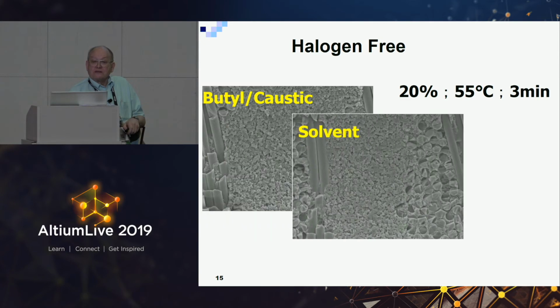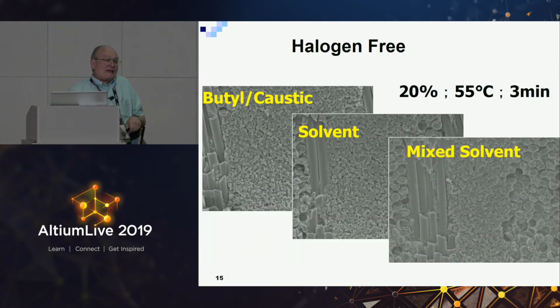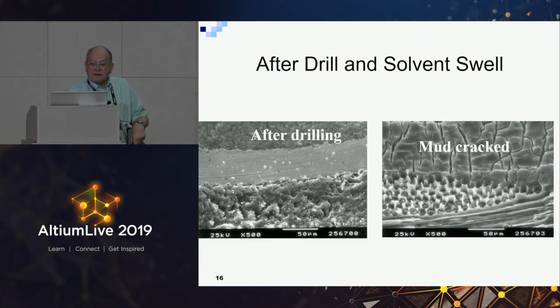The problem is that the halogen-free has a different smear because they've changed the resin content. So depending on the materials you pick, have the fabricators done their homework in terms of adjusting the smear removal process to match this particular kind of halogen-free? The materials are not all the same. After drilling in solvent swell, there's a thing called mud cracking. In other words, the improper solvent swell cracks the resin. And as you crack the resin, you now introduce a field failure mode, because it's the wrong concentration for that type of resin.